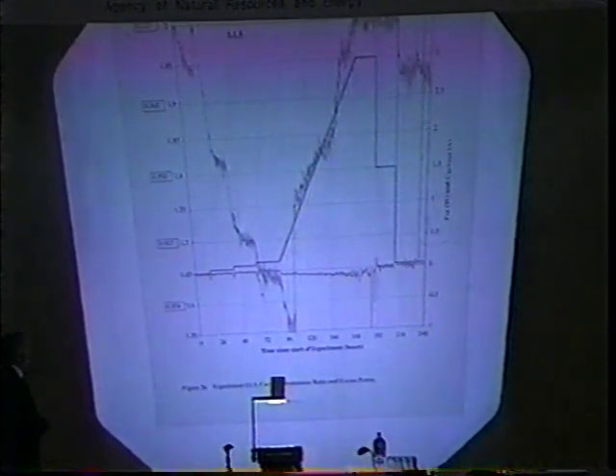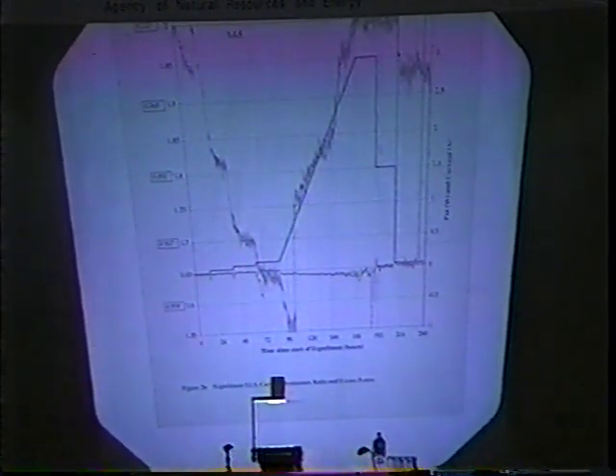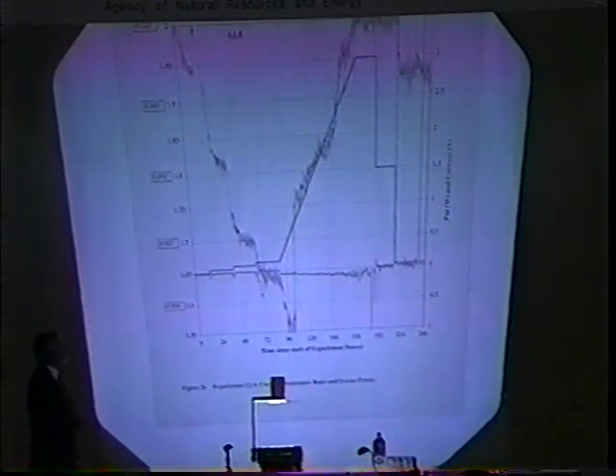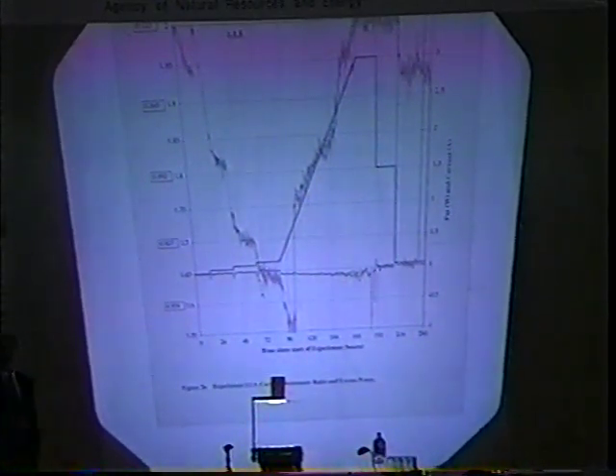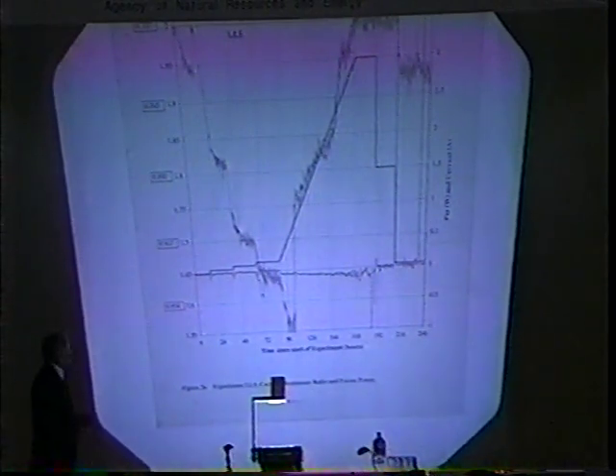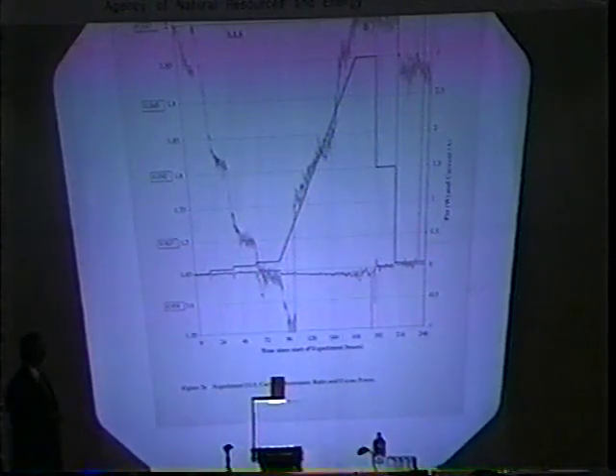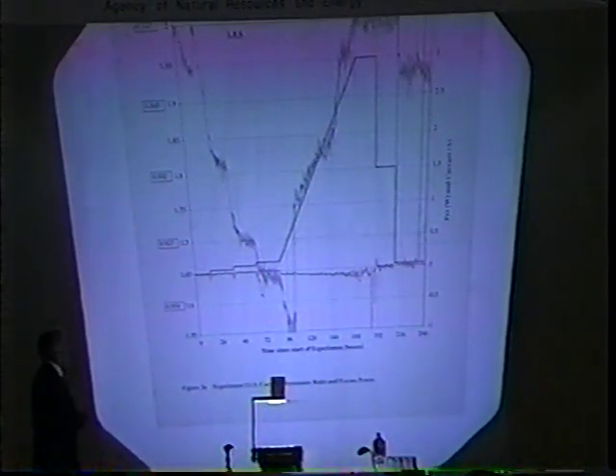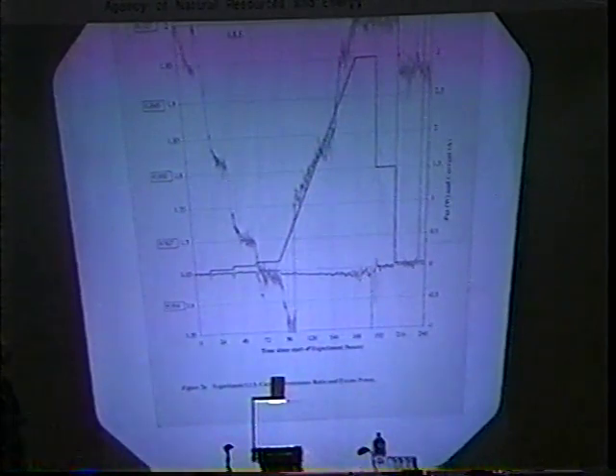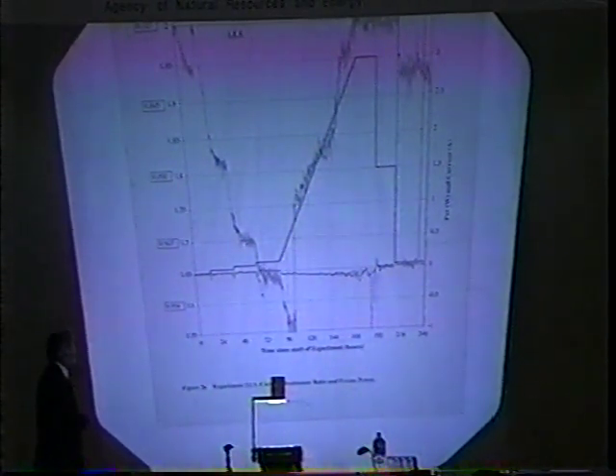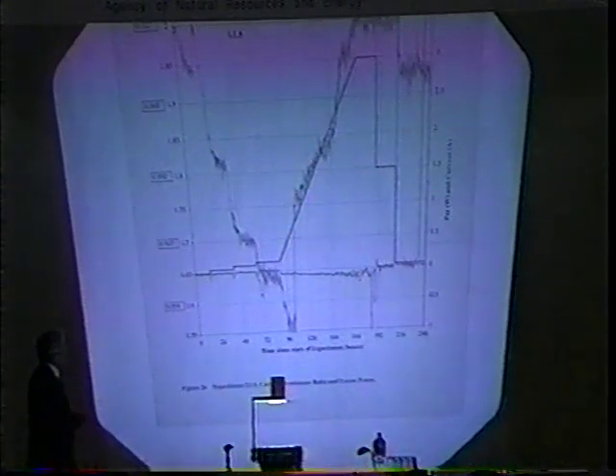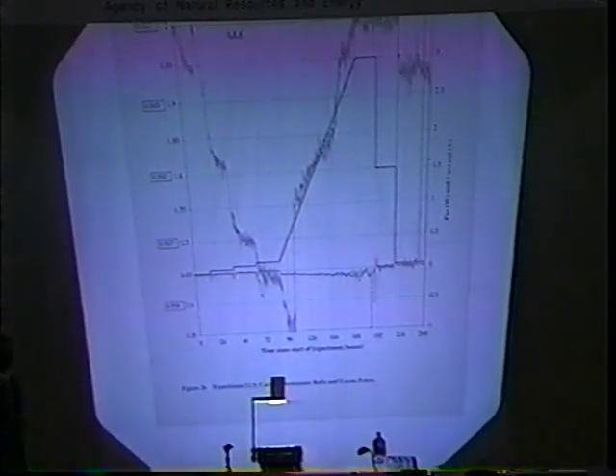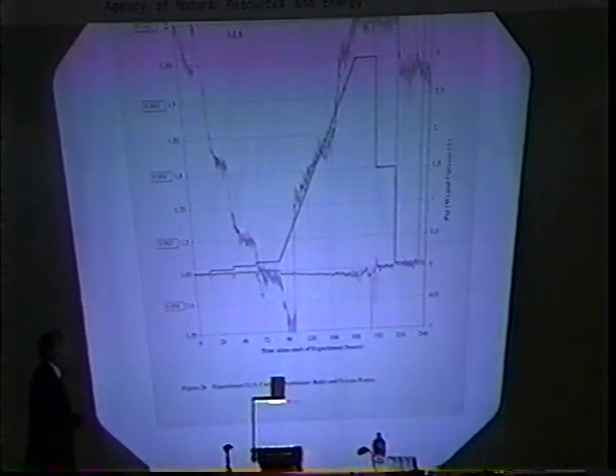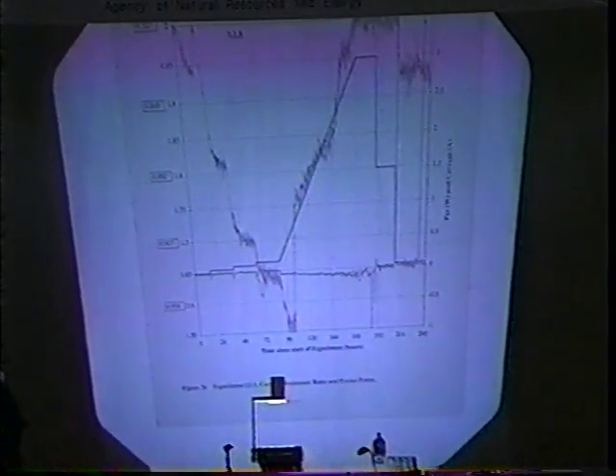It lost about 10% of its loading in a period of an hour or so. This is the norm. This is what we normally observe in 1996. It is not what we normally observed with our first lot of palladium in 1989 to 1992. As you can see, the calorimetry during this time is sensibly balanced. There's no significant level of excess power associated with this effect.